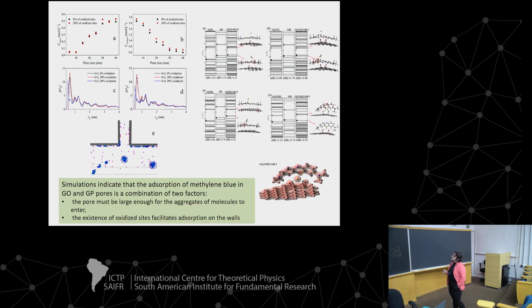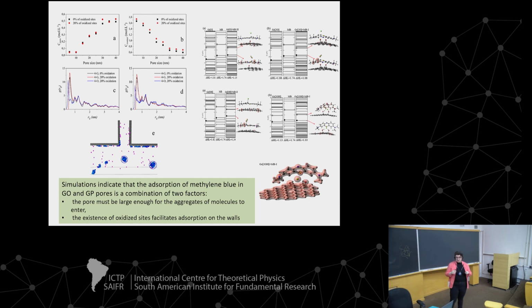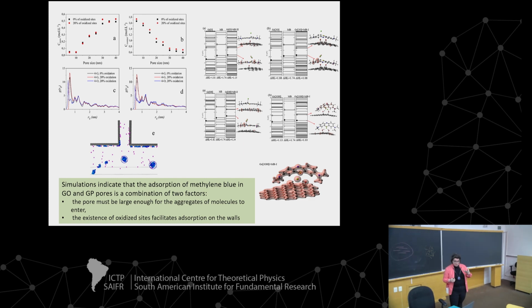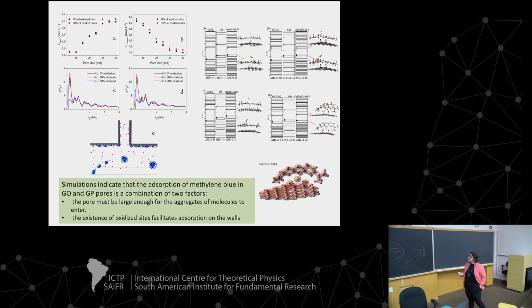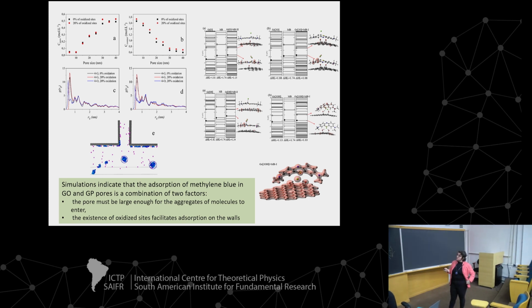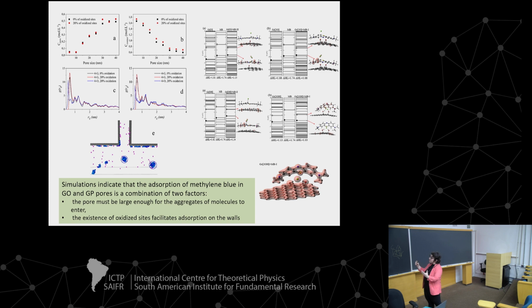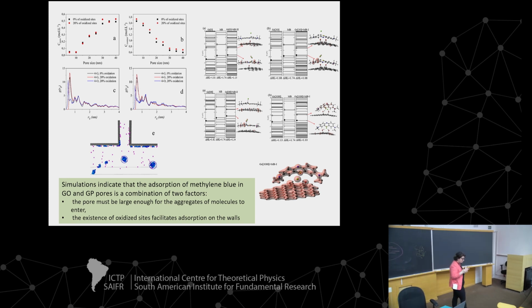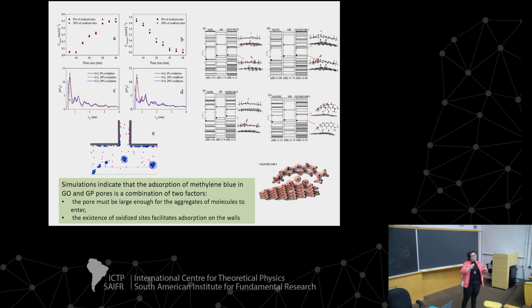We discovered that the simulation indicates that the adsorption of the methylene blue in graphene oxide and in graphene pores is a combination of two main factors. The pore must be large enough. These two intermediate materials are more porous. The pores of the intermediate materials are huge compared to the other two. So our materials have pores large enough for the aggregates. Again, this methylene blue dye forms aggregates. And when we have huge pores, these aggregates enter and can be adsorbed in the graphene sheets.